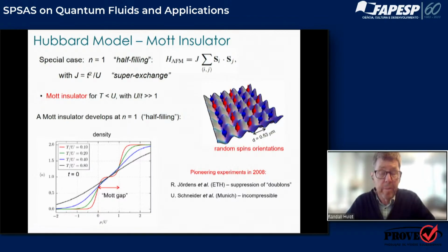There were some very nice experiments, both in Tilman Esslinger's lab at ETH and in Immanuel Bloch's group in Munich, in which they demonstrated back in 2008 that a Fermi gas would manifest the Mott insulating state as a suppression of doublons, double occupied states, and also that it would be incompressible. The change in density with chemical potential would go to 0, reflecting this horizontal Mott gap.